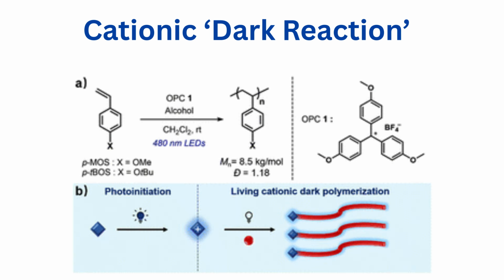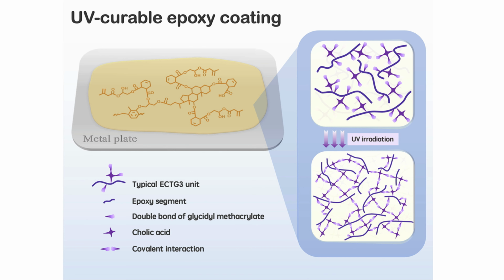By contrast, free radicals are extinguished by a variety of bimolecular termination steps, and polymerization quickly ceases in the absence of light. Furthermore, cationically photopolymerizable monomers and reactive oligomers are generally characterized by inherently low levels of toxicity and irritation, and for this reason are good alternatives to acrylates and methacrylate systems usually employed in free radical photopolymerizations. In addition, the lower volume shrinkage observed in the cationic photopolymerization of epoxide monomers affords better adhesion properties as compared to the corresponding radical-based systems. Last but not least, photopolymerizable cationic systems possess better inherent mechanical properties and thermal resistance than their corresponding free radical system counterparts.